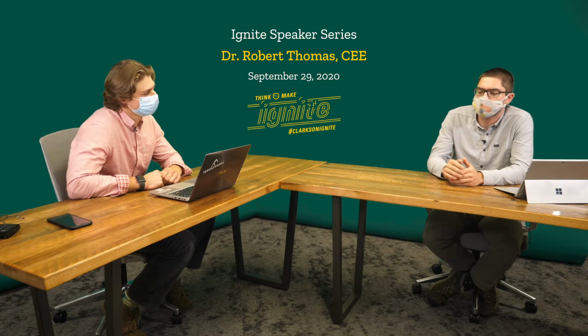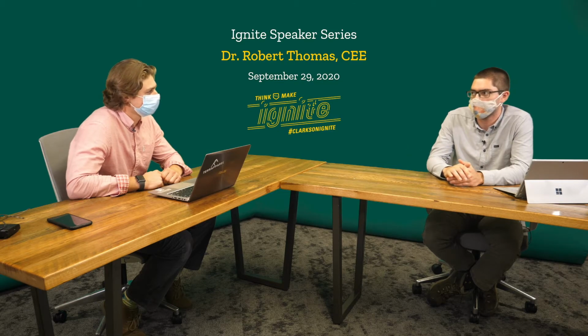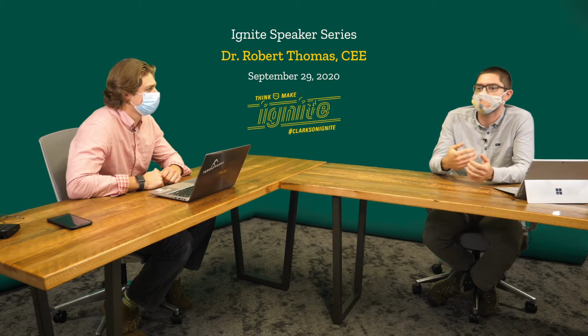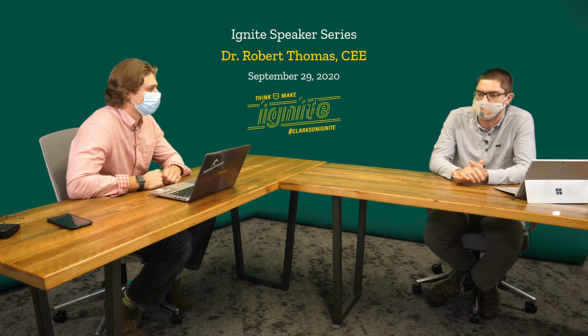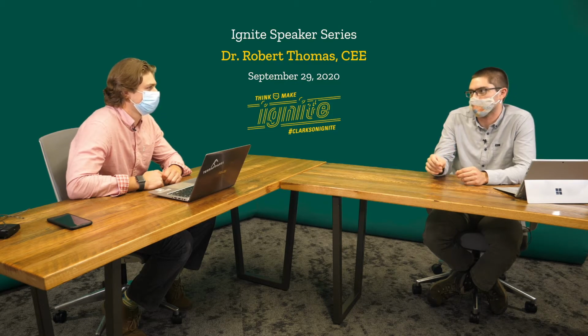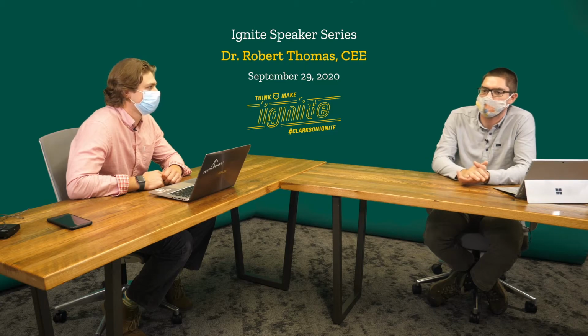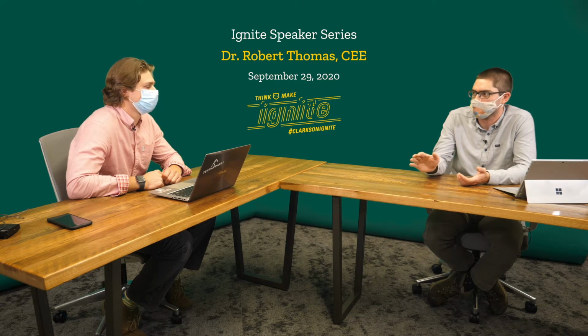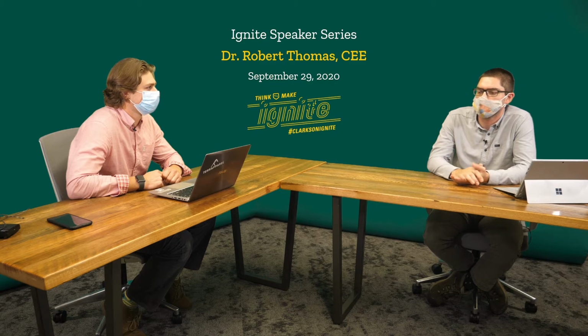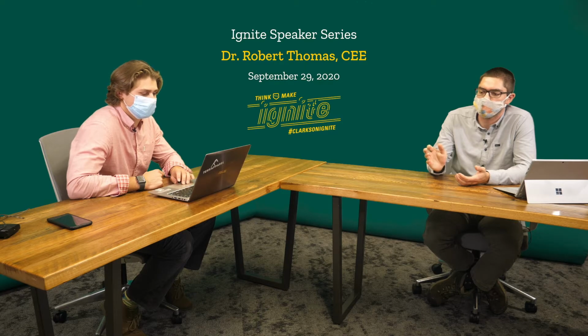The other thing that's restrictive is that a lot of the fly ash that we are still producing, because of the coal supplies and all of that, is very low quality fly ash. And we are not allowed to use that at all because there are some arbitrary standards that specify your fly ash must have this much calcium oxide, it must have this much silica. And if we miss that specification by a little bit, that material is completely excluded. That's not good for us because we can't use it in the concrete. It's not good for anybody because that goes in a retention pond. And if you just take a quick minute to Google fly ash retention pond failures, they are an environmental catastrophe.